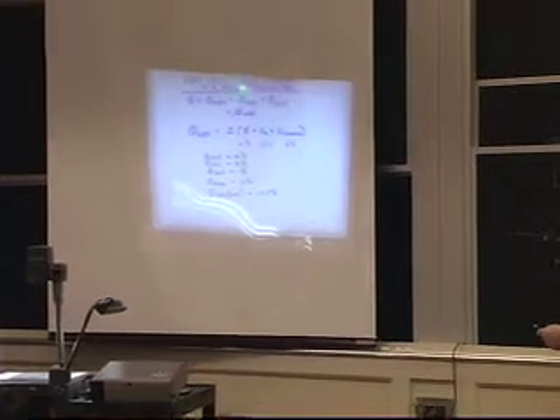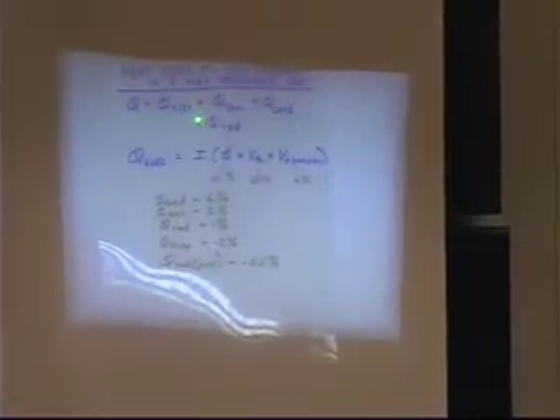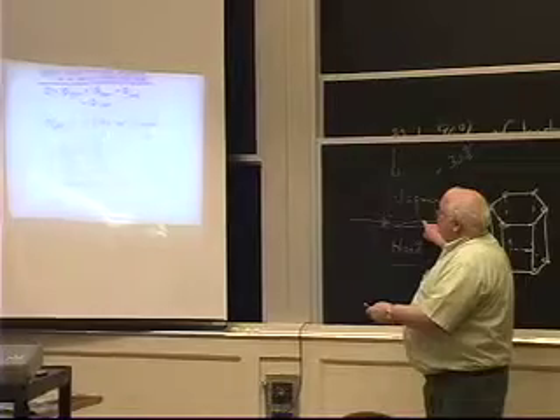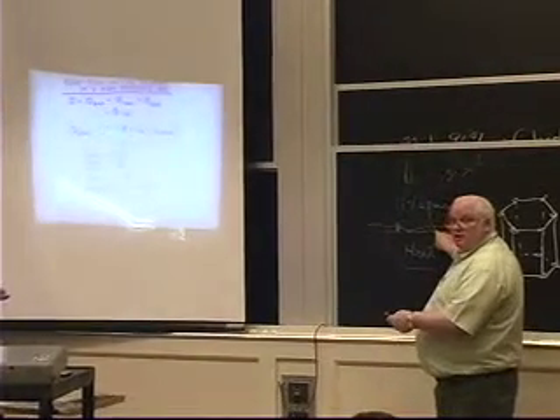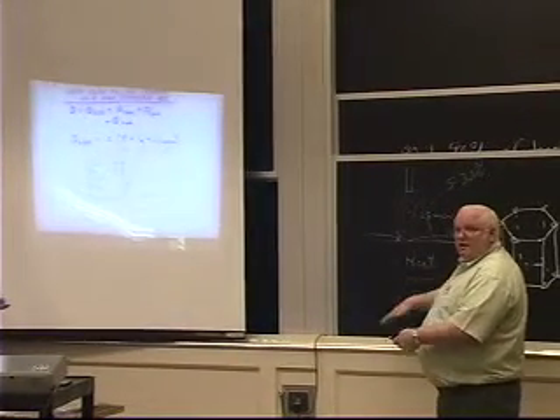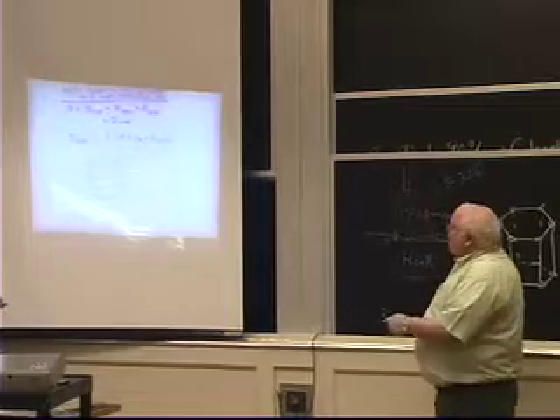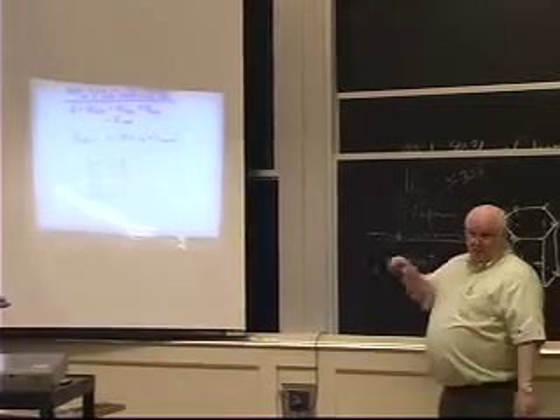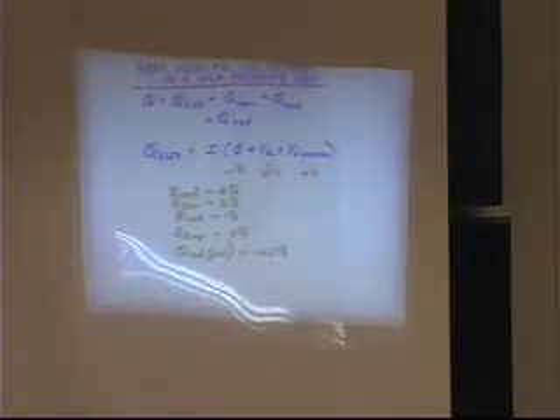Every electron is carrying energy. So it's the current times the Thomson energy, the hot gas, and 1/2 MV squared in the gas energy, because they're going to be moving a lot slower down here, at a much lower temperature, and therefore moving slower. The anode voltage drop, which is coming across here, and then decaying down to the energy level of all the other electrons, that's how much heat is given off by the electrons coming through here, which is 80 to 90% of the total heat getting to the surface. So they are absorbed by the metal.